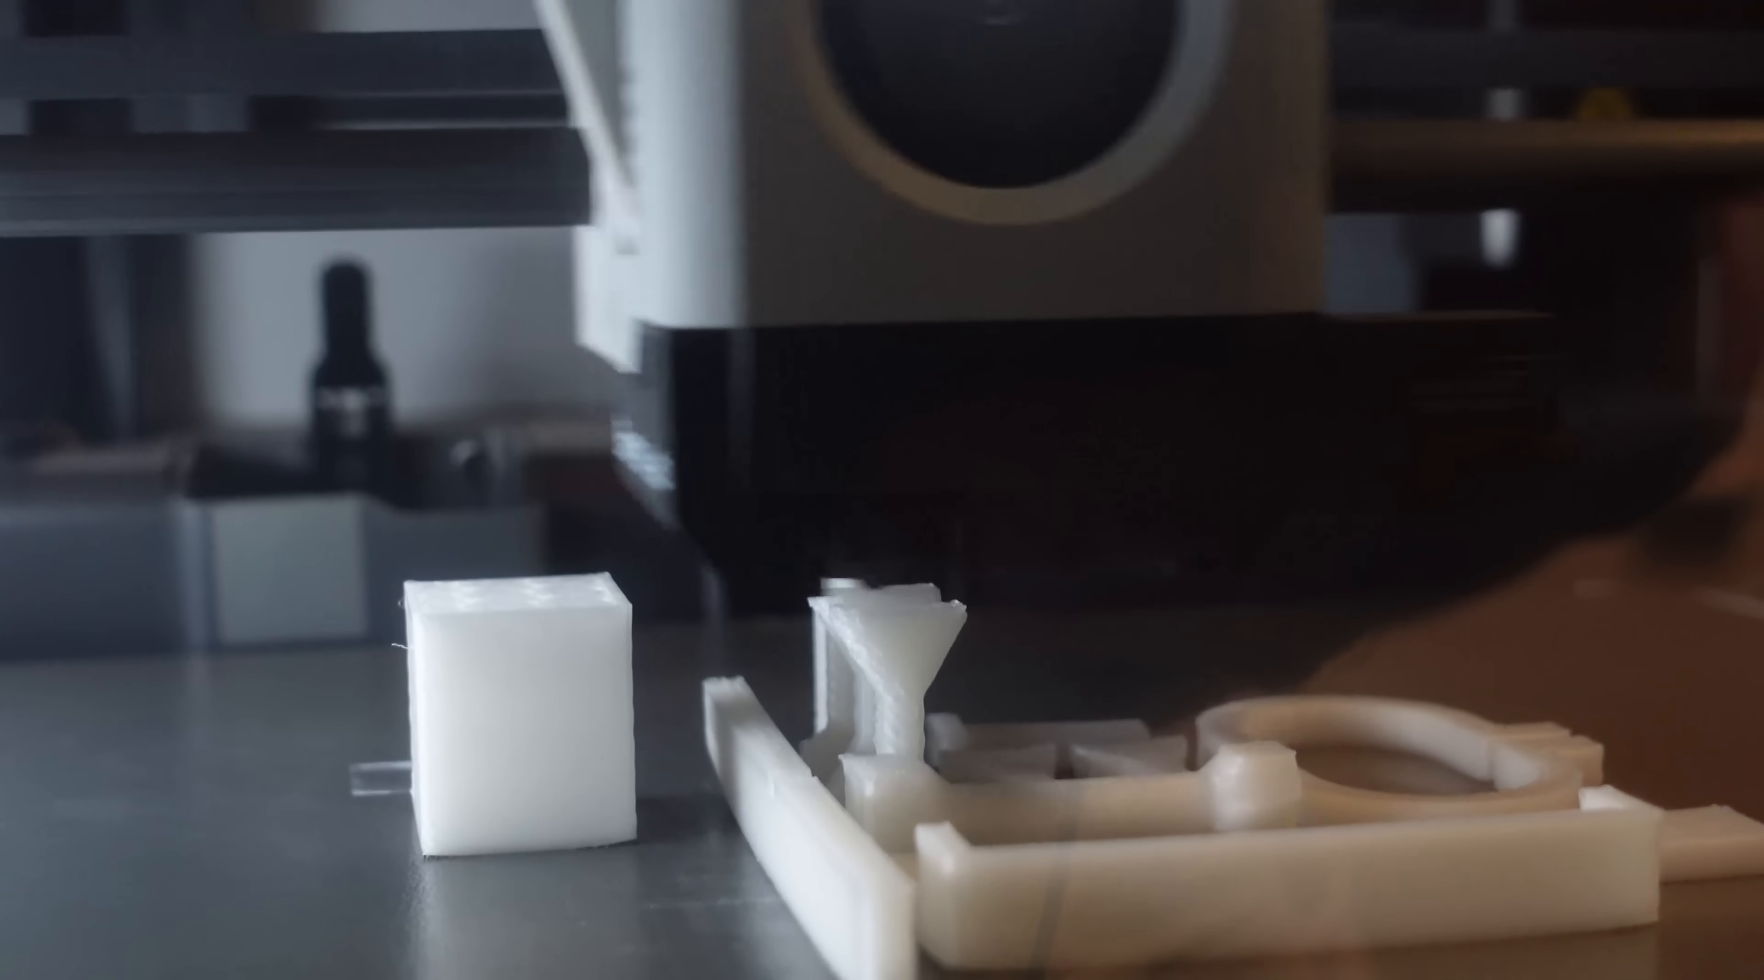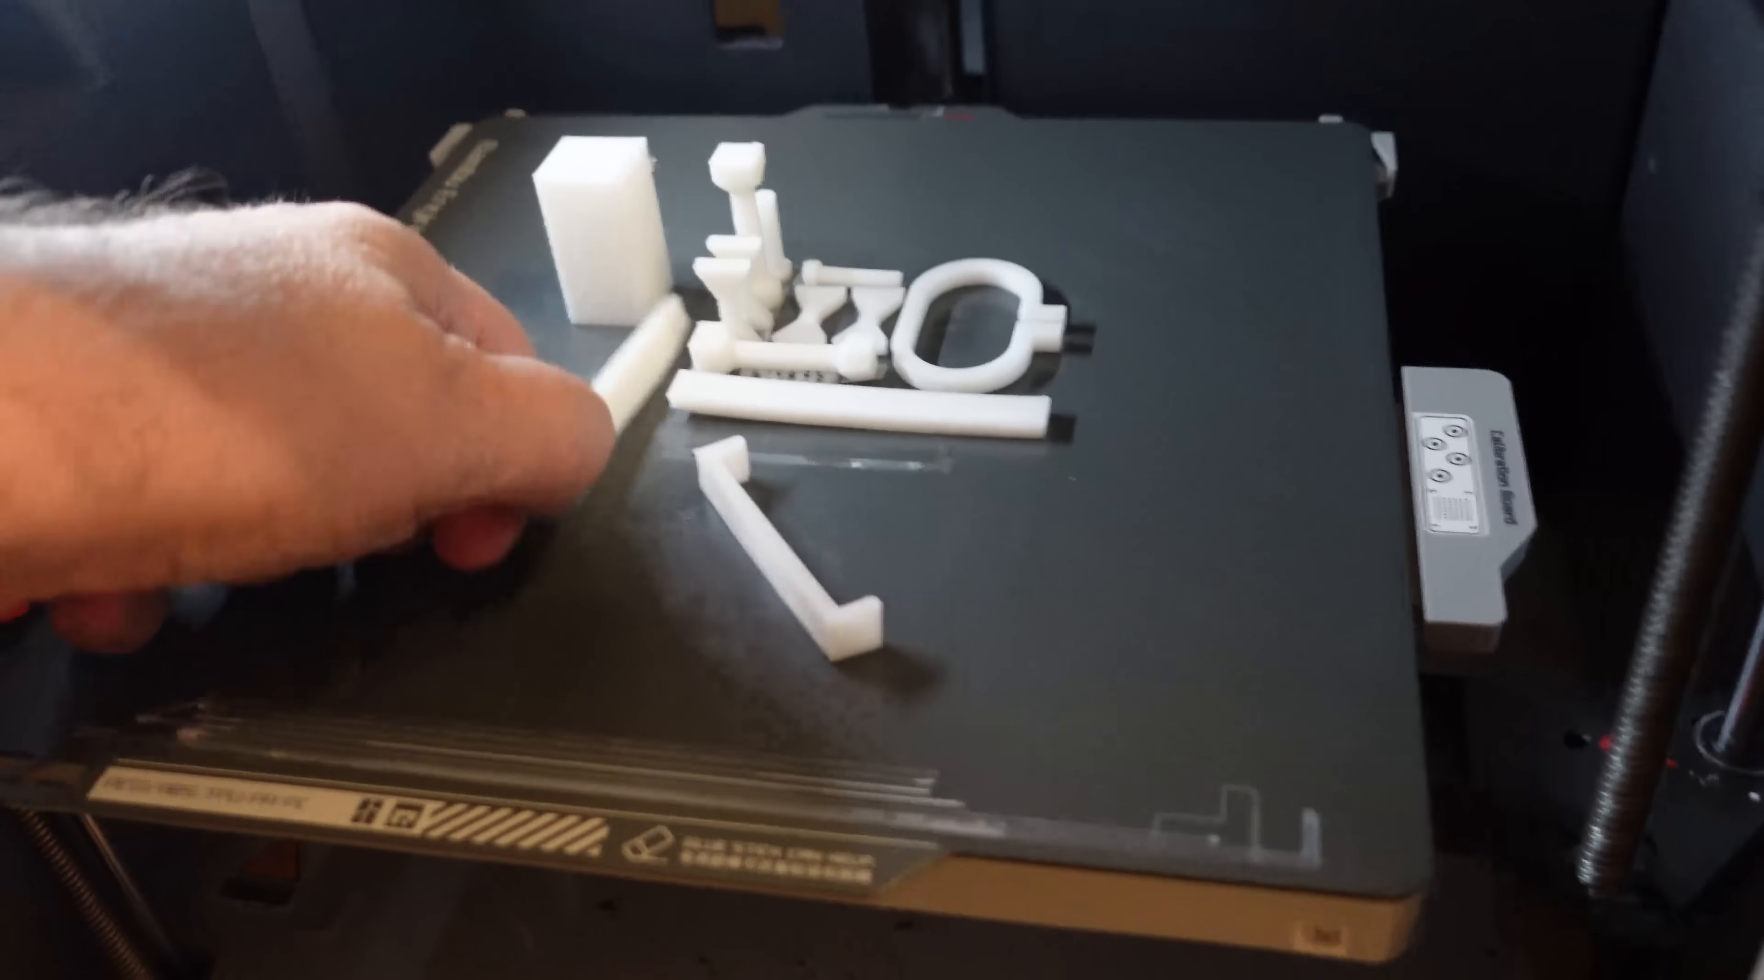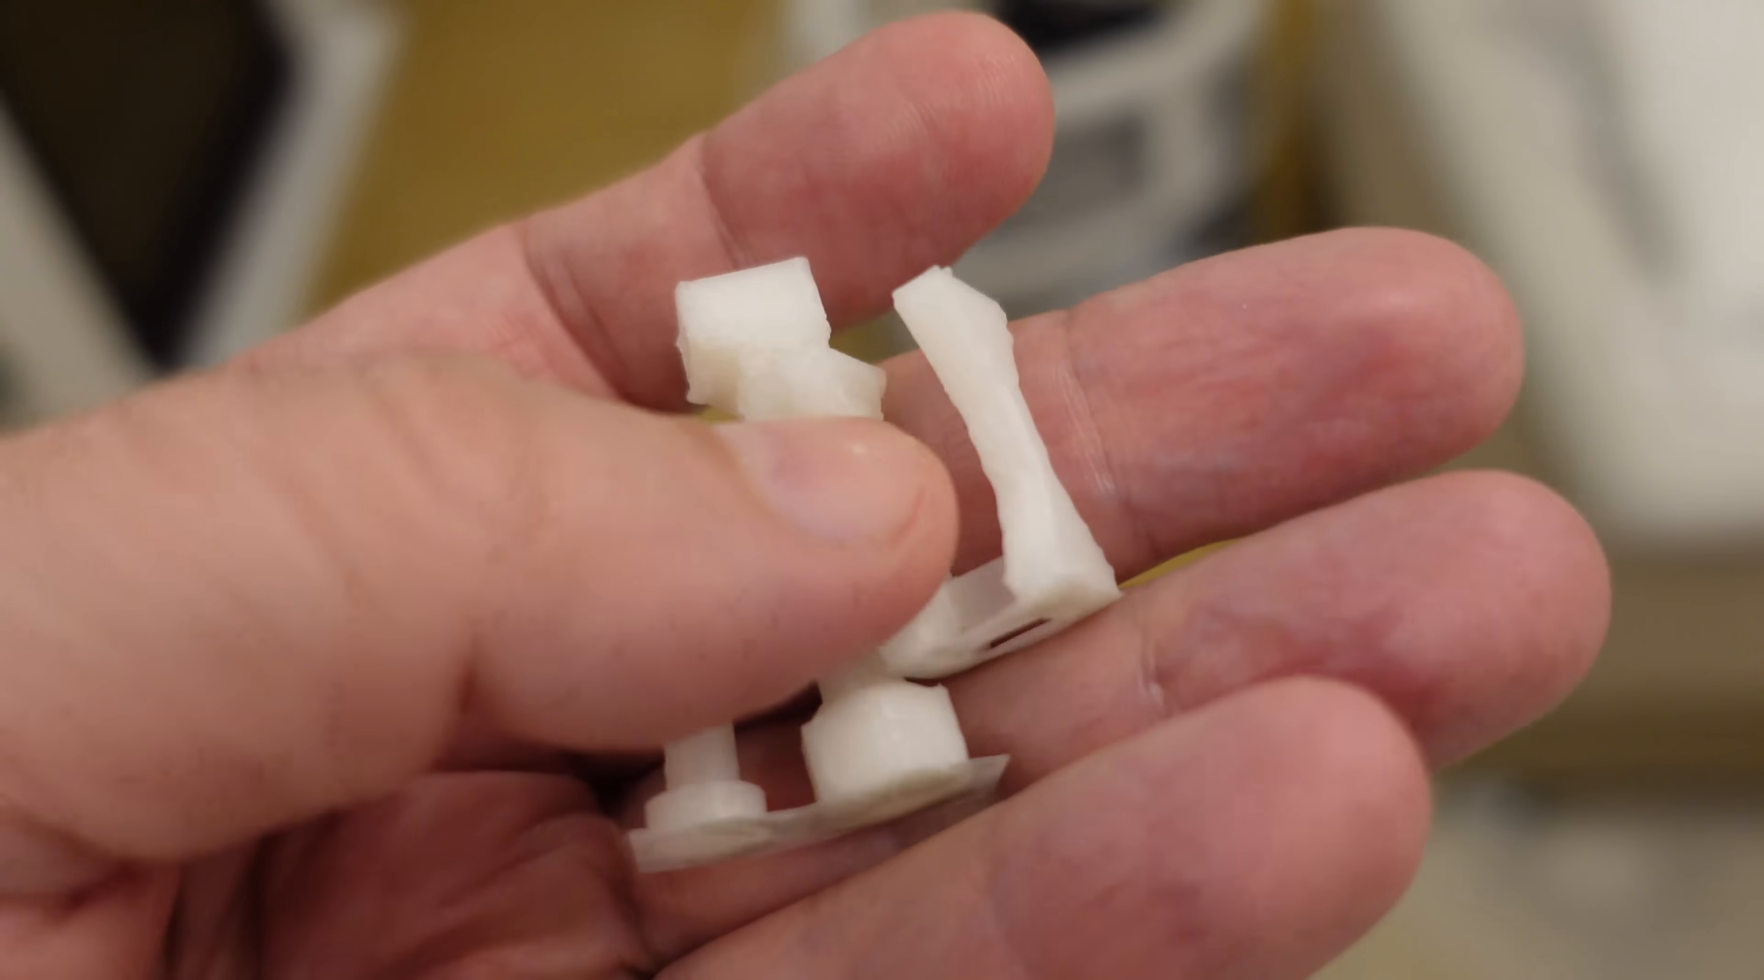Everything else looks okay so far. I will analyze them later, I am not at this moment sure if this part cooling is enough. At least I hope they will be finished. And this was the last covering layer on the test object. Printing is finished, but before I open the door I want to enable the chamber fan a little bit. I don't like the smell. The bed cool down, let's analyze them. Okay they are removable thanks to the glue. First let's check the warping, and in worse condition is this one for the impact test. It is measurable because in the middle it has that cross section, but I will try to reprint this on Qidi Plus 4 with actively heated chamber. Now let's take a closer look of these. Actually they are not so bad, this is my reference for the printability of the filament. It's printed, not the nicest overhangs, but it is measurable.